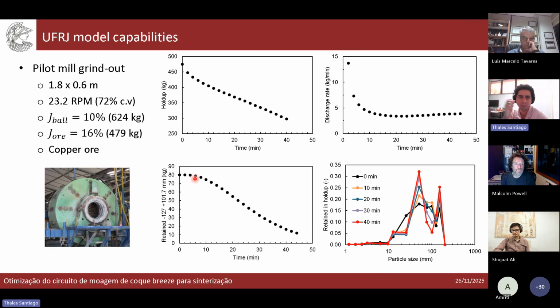So just to show you some of the model capabilities, this chart shows a simulation of a copper ore pilot mill grind out test. It predicts the discharge rates, as you can see here, of fines, and the hold up of the coarse rocks through the entire simulation time span. You can see here the top size lingers inside the mill for a moment, and then it rapidly breaks.